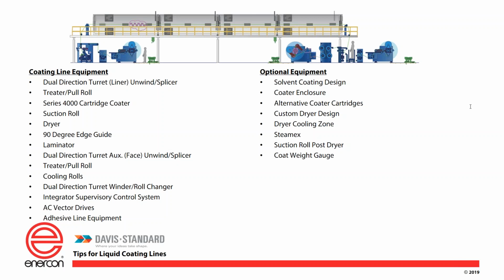Then we go through a final cooling section where we bring the web down to less than 100 degrees, near the ambient room temperature, so that as you wind it, the roll stays stable through the rest of your process. You also will have on here a mainline controller, which we call an integrator supervisory. That runs the whole line.